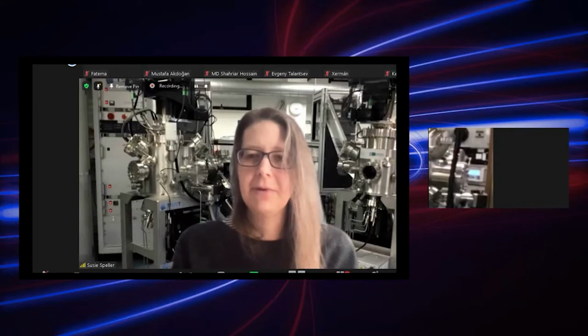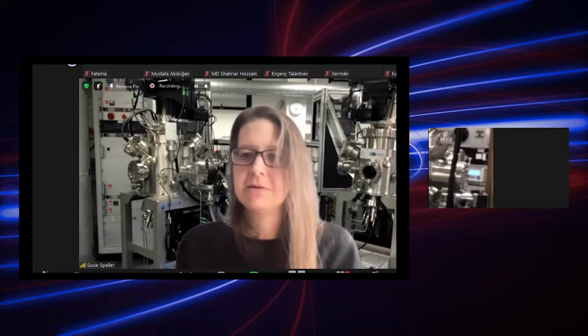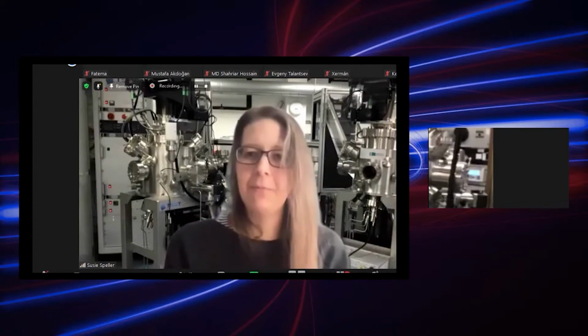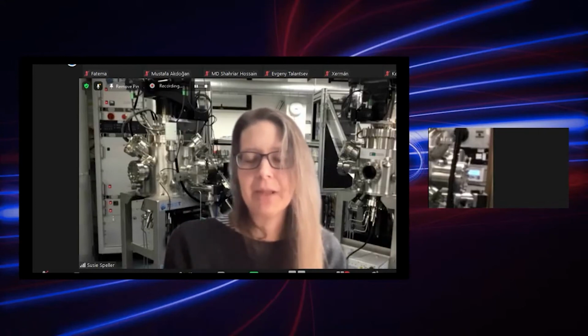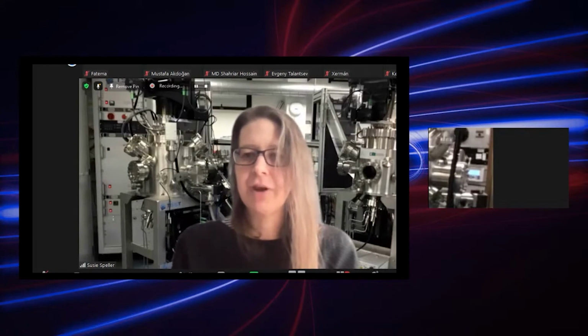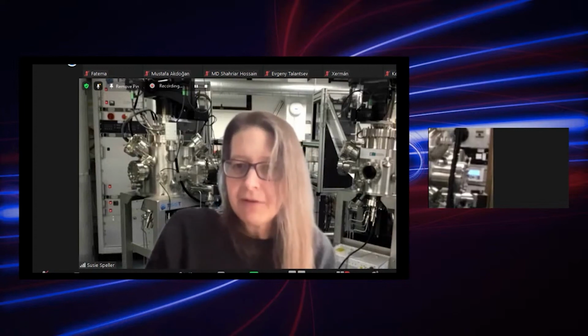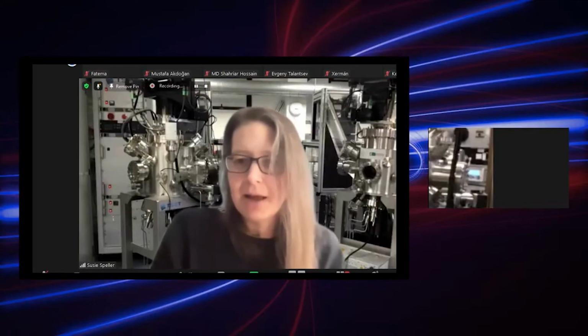We have made larger samples with them. The problem with the very ultra high pressure technique is that the samples crack if you're not careful. So we had some successes, but it's often the case that you get cracking in there. What we haven't done yet, and what Element 6 are absolutely sure we can work out, is the way to take off the pressure in such a way that we don't crack them during the cooling down process and the removal of the pressure. So that's the big difficulty with the ultra high pressure. It may seem like a very extreme technique, but because it's industrially used, it could be used and could be scaled.